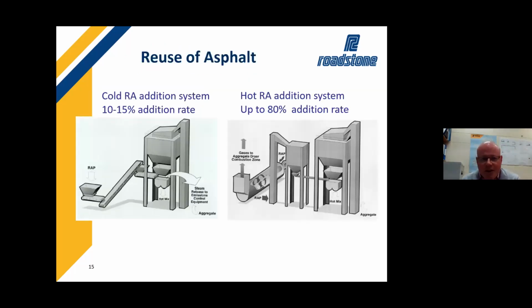How do we recycle it in the asphalt plant? So you saw a quick overview of the plant. There's two systems really that are in use in Ireland. You have a cold feed system, which is a hopper that feeds directly into that mixer, the pug mill mixer. So as the aggregates come in hot, the RAP comes in cold, and that gets mixed, and moisture is driven off with the elevated temperatures of the aggregates. That steam is taken away, and then the bitumen is added in, and this is all mixed together, and you get your final material. Otherwise, on the right hand side, you have a hot addition system.